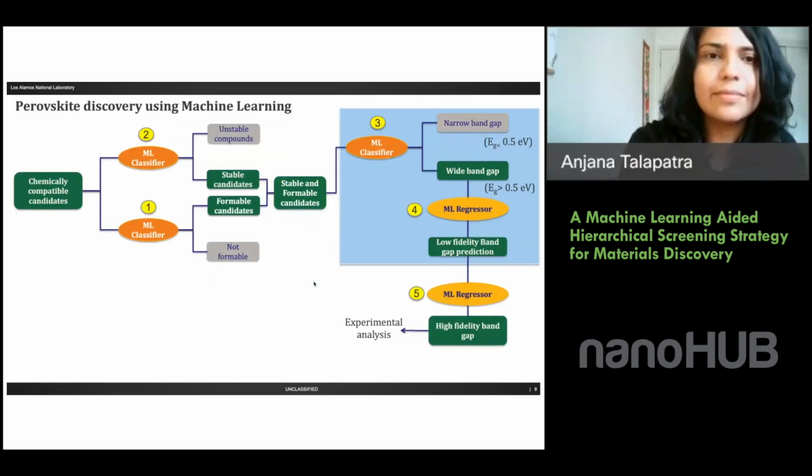What he's getting at is that I focused this talk on perovskite discovery, but the larger goal is to find new scintillator materials with wide band gaps. We are looking at oxide perovskites to find these materials. That is a good question. Why do we need a wide bandgap material for a scintillator? It's not necessarily that you need a wide bandgap material for scintillation, but you at least need something which has a band gap, let's say. There is much more to the problem than having a wide band gap. You need to know whether the activator states are in the correct levels or not.